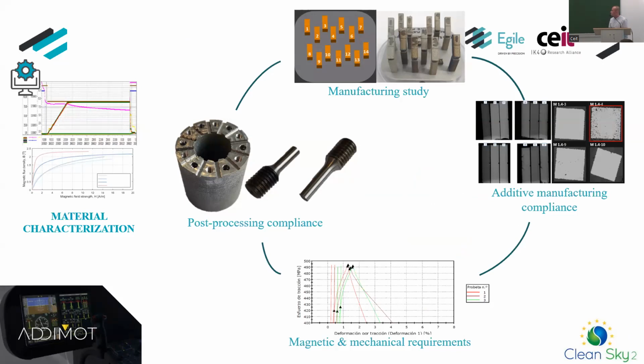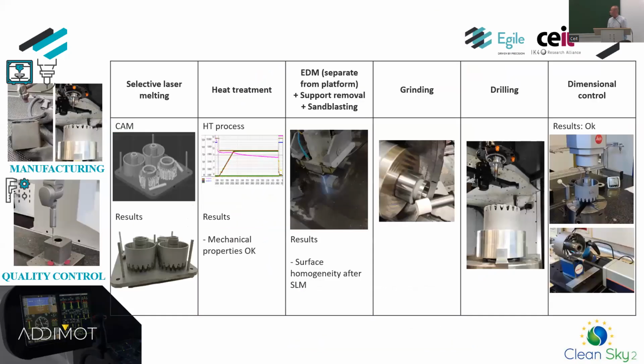Before starting with the manufacturing of the prototypes, we made some test tubes in order to check mechanical and magnetic properties, and some test tubes in order to check machining cutting speeds. You can see some grooves, some holes, some threads, similar to the final design. Here you can see the manufacturing batch of the soft magnetic material Permendur. In this case, both rotor and stator have been manufactured in the same batch, along with some control height porosity bars that have been checked in CT scan.